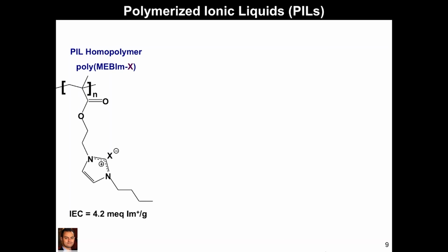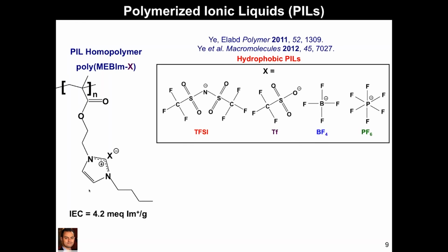This is one that we've synthesized in our lab, and others have too. So you can see here that the backbone is a PMMA-like, polymethyl methacrylate. And here you can covalently attach a commonly known ionic liquid, an imidazolium-based cation. And then just through ion exchange metathesis, we could look at a variety of different counterions. And we've done this, and others have too. And so here's a typical class of counterions, and they're fluorinated. This is typically what you'd see in ionic liquids.